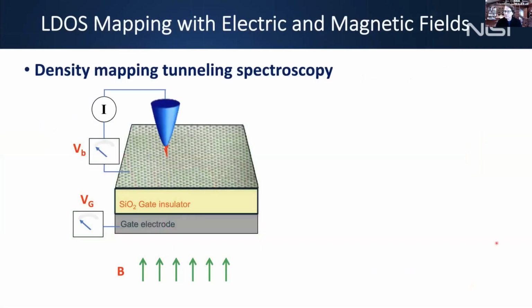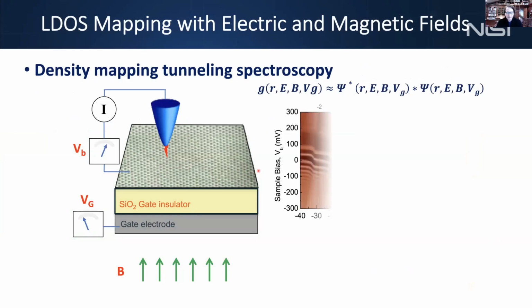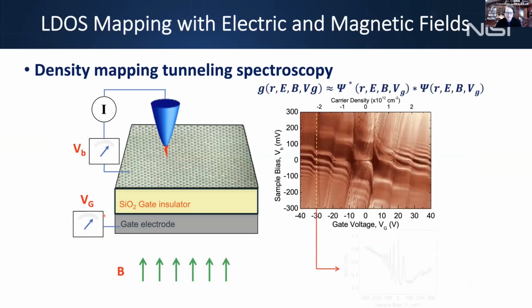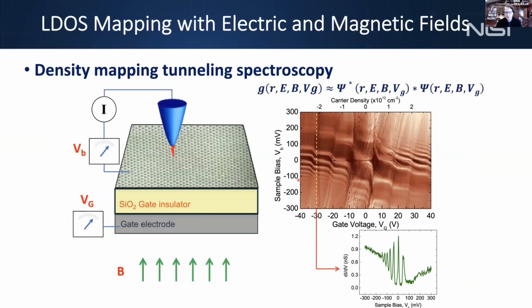Then we have to perform our spectroscopy, this is how we do it. You can call this density mapping spectroscopy because now we have a backgate. And so you can take spectra as a function interleaved with the backgate electrode here, and you can create a spectral map. You can do that as a function of position. And so then you can create a map that's a function of spatial position, energy, magnetic field, and density.